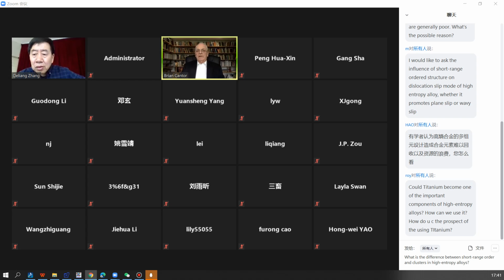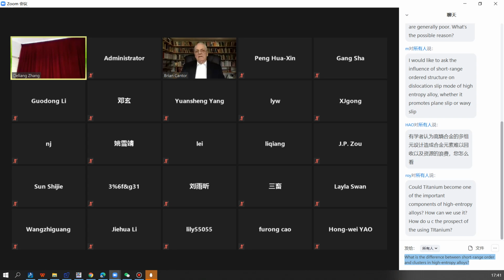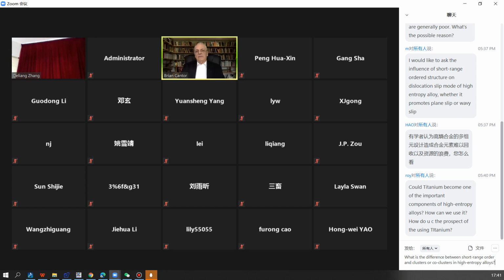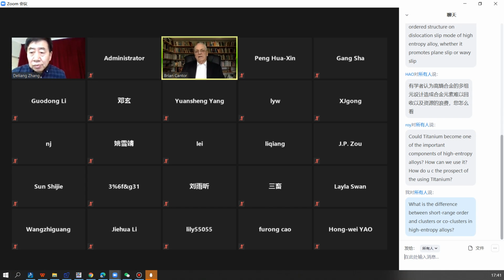Well, I didn't talk much about short-range order, but of course, the Cantor alloy itself. So let me just deal with the Cantor alloy itself, which has got 20% of chromium, manganese, iron, cobalt, and nickel. Now it's very near to being a regular solution. In fact, it's very near to being an ideal solution. There's been quite a lot of study now which shows that it's got very little short-range order in it. There might be a little bit of short-range order. There's a little bit of a tendency of manganese and nickel to congregate together rather than iron and cobalt, and so there is a very slight degree of short-range ordering, but it's very, very slight. It's almost undetectable. So the Cantor alloy itself is, I think we can say to the best we can measure, ideal.